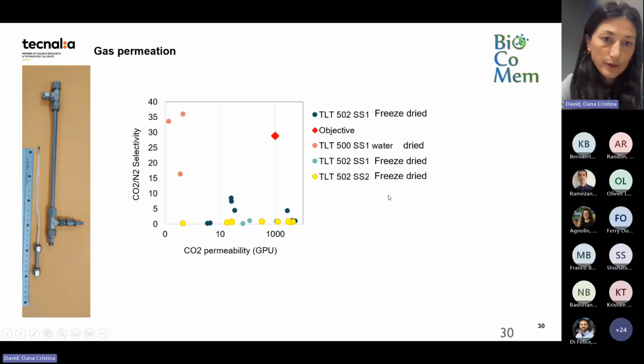So here I show some gas permeation results. When we dry the fibers directly from water, we managed sometimes to achieve good selectivities of 30-35 at very low permeabilities. And because we basically achieved dense tubes, the porous structure collapsed. When we dried them by freeze drying, we did manage to keep pores open, but they were defective.